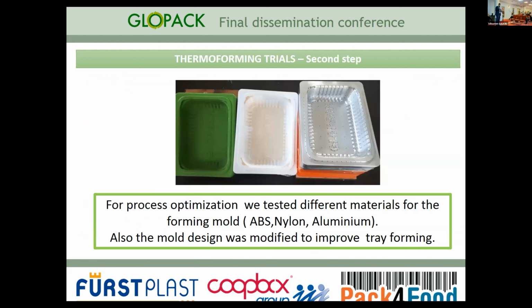So after that, we started working also on the mold, because for the laboratory thermoforming machine, we started using some 3D printed molds made of plastic. The first plastic we used was ABS, but we found out that since the forming temperature is quite high and also the time is quite high, the mold became soft, so it started melting.